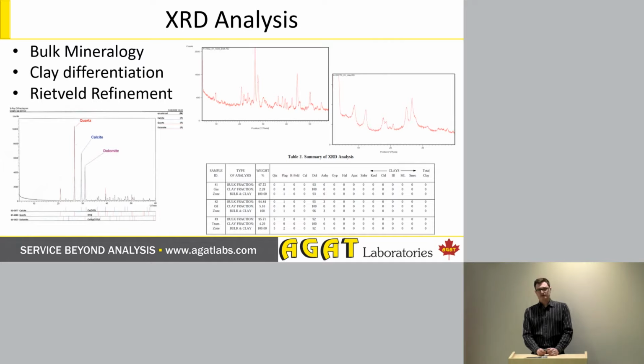XRD gives us the clay mineralogy. That is, it gives us overall mineralogy, but its number one advantage is it can give us all the clays and differentiate them quite nicely. It's an industry standard tool for doing this, and we now do it very effectively using Rietveld refinement where possible. When we do have a lot of smectite and mixed layer clays present, we actually cannot use Rietveld refinement. The patterns cannot be refined using that mechanism, so we revert to a somewhat older technique called relative intensity ratio.